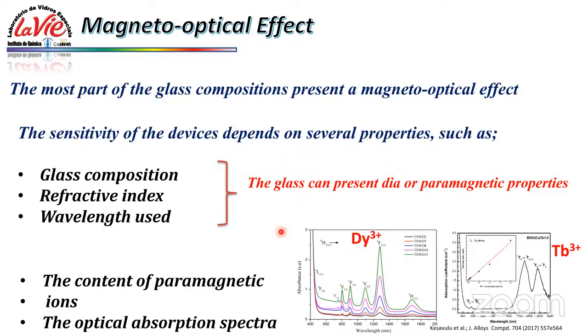In this case, we also need to take care of the optical absorption spectra of the ions. Here I just put two examples, dysprosium and terbium. As we can see, when we have a high content dysprosium sample, we have absorptions in the infrared and the visible region. To work with the magneto-optical effect, we need to avoid the wavelengths where there is some absorption. Terbium is one of the most used ions to study the magneto-optical effect in glass, because it has only a low absorption in the region of 480 nanometers, and then other absorptions in the middle infrared.